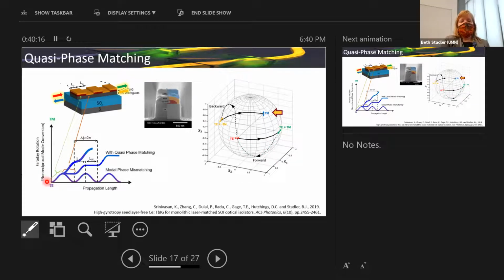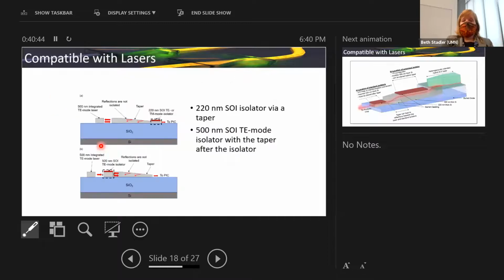But see over here, if you had negative and then positive, see where this light wants to turn back to TE, if you change the sign of your gyrotropy or your Faraday rotation, you'll swing back up instead of staying level. Then swing up because it's negative, then positive, then negative, then positive, and so on. Turns out you can get a full mode conversion, or we only need a half mode conversion, in a fairly short spacing.